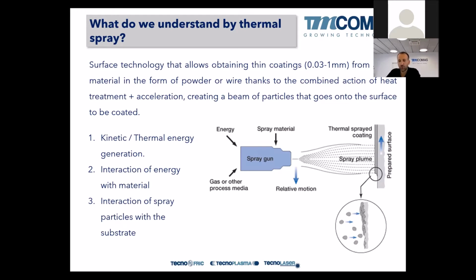So those technologies allow us to obtain thin coatings from a material in the form of a powder normally, or also some of wire, but normally we work with powders, thanks to the combined action of heat treatment and acceleration that takes place in the gun. The gun is a device that can be moved by hand, by robot, or by a mechanical jig that will move this spray of molten or semi-molten particles that will be accelerated because of the expansion of the gases, or because of the pressure of the input gases, to create a spray of hundreds or millions of tiny particles that will go into the surface to be coated.